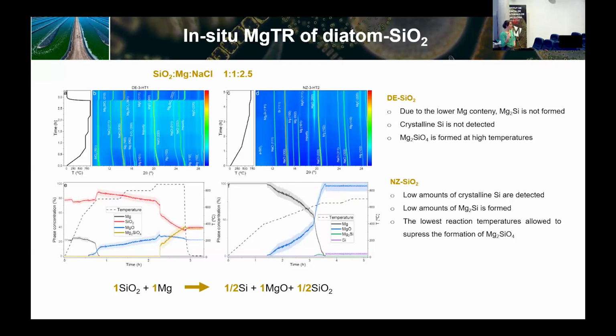Meaning that if we have magnesium silicate, it means that the temperature inside the reactor is much higher than what we think, and that we can control the formation of this phase just by somehow lowering the temperature of the reactor. These are good news because it means that we can have some practical guidelines of how to do this.